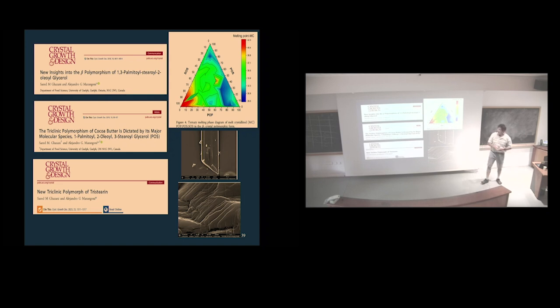People had missed it, and I should have put here the picture of Saeed Ghazani. He crystallized the material from solvent and waited 2 years, so that you get an idea of how long it takes to get to the final crystal form. So maybe it's not so fast in the solid state, the transformation, but the melting points were between 30 and 36. The literature was a mess. But if you wait long enough, you get to the polymorph, 2 years from the solvent.